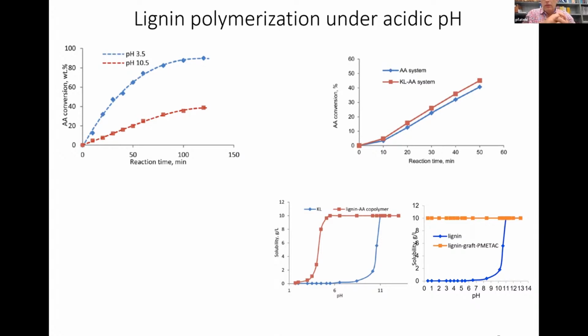So as you know, kraft lignin is not water soluble at low pH. So we had a suspension polymerization system, but we got much better results. So you can see that the blue line here is we have much better reaction. We had much better system, and these are the products.